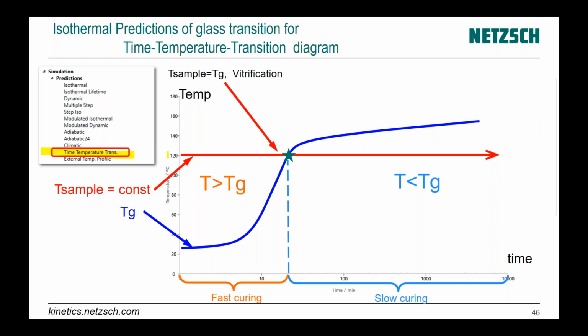What is it? Let's speak about isothermal conditions. Here is the temperature of a sample over time, and the glass transition temperature of the polymer at the beginning is somewhere below the current temperature, and at the end is above the current temperature, and somewhere there is a crossing. In the first period we are above glass transition, we have fast curing, material is elastic or viscous liquid, and after this point we are in glassy state and curing is very slow - this point is the vitrification point.